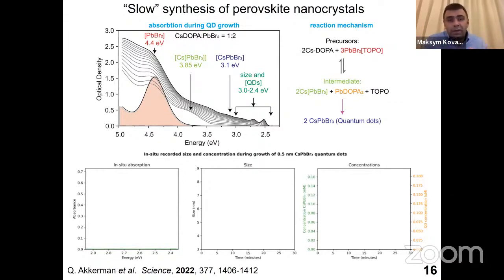One way to accomplish that, and I believe there are many ways to accomplish this, but one is that, again, you don't use any amine. You use lead bromide and trioctylphosphine oxide as a molecular adduct, which dissolves at room temperature in hexane, and you inject cesium salt. So the only cesium in this synthesis is in the ionized form, more or less. The other precursor is fully molecular. And you see the absorption spectrum of this lead bromide TOPO adduct in the UV-vis spectrum.